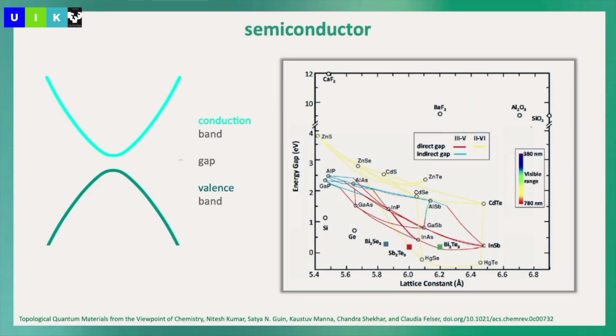So simply by starting with the semiconductor, now bringing this to real life is, as I said, the nice prediction from Charlie with the graphene and the spin-orbit coupling, and that this could be leading to a quantum spin Hall effect, is like looking for something which has a valence band, a conduction band, but has this band inversion, because we learned already we have to have this transformation, so that we have this crossing point, this topological critical point.